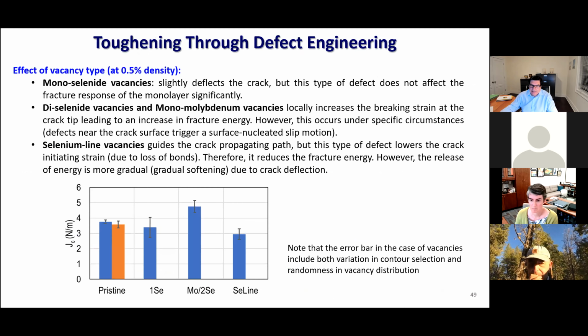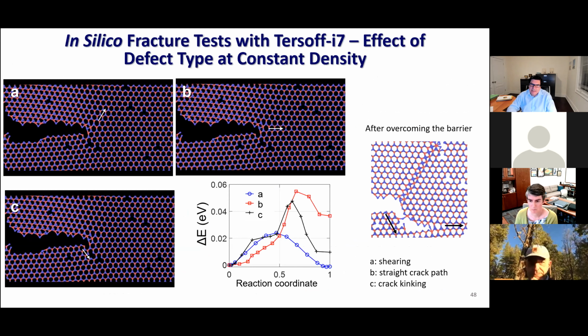The only interesting arrest, which is probably relating to toughness, is when we saw a certain environment of the defects that energetically favor shearing of the lattice, like a dislocation emanating. And people talk about dislocations in this material, but it's very different than metals. And you don't get these emissions of defects because of the 2D nature, exactly what you are mentioning. When you stack multi-layers, the stacking is such that the interaction between layers is very weak. It's more van der Waals. So certainly it will introduce, especially if there is confinement or other features, more interesting behavior may emerge.